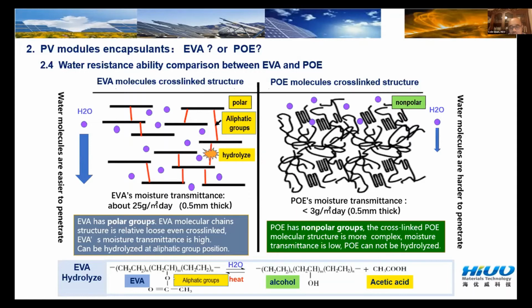That is why we need to control the backsheet moisture transmittance, because if too much water comes into the module, it will be hydrolyzed and turn into acetic acid. This material will cause a lot of trouble, like PID, like corroding the cells. And this acetic acid can also accelerate the hydrolysis reaction. So as an encapsulant material supplier, we also need to formulate the components of the encapsulant material to control the presence of this acetic acid in the system.